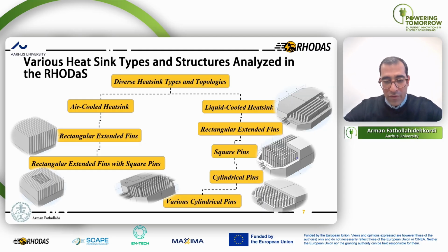And one of the key important things in the liquid-cooled heatsink was the hole that we built into the heatsink. It was very difficult to handle this hole because in the printing, building and manufacturing of these heatsinks, it caused a lot of problems. But after that, the result is you will have a good mounting pressure. That is very important.